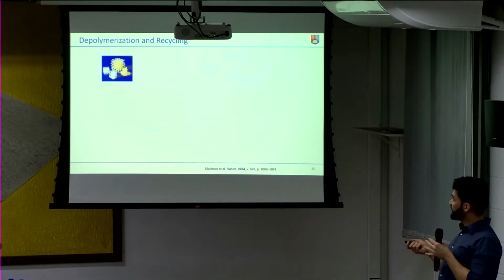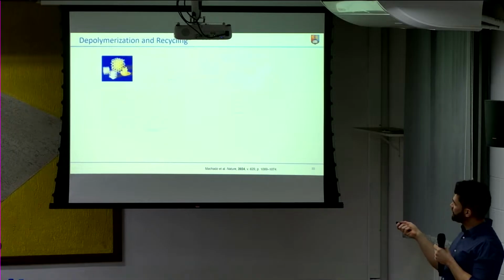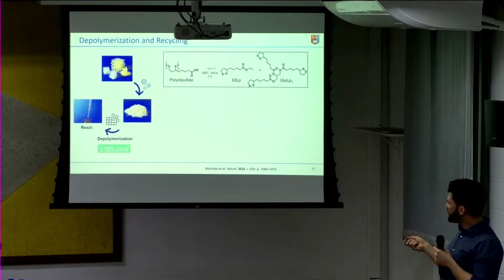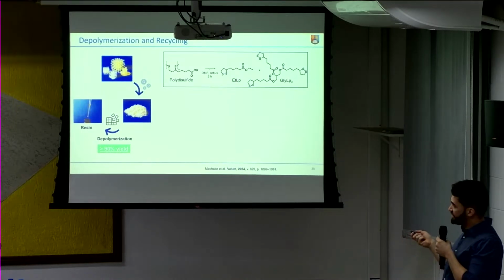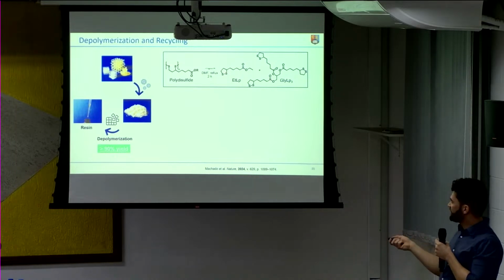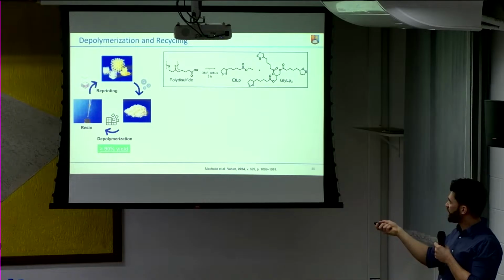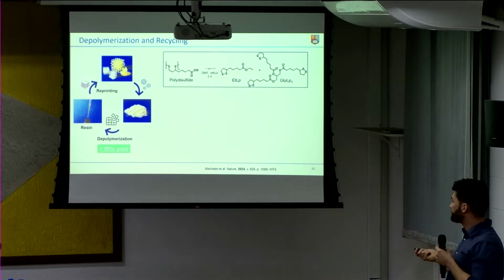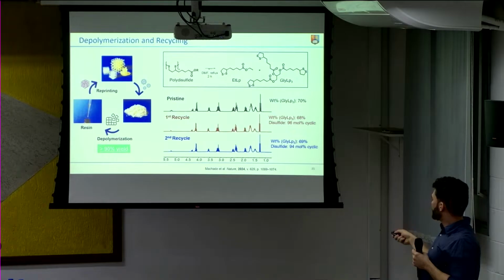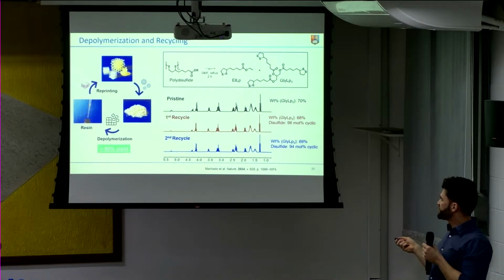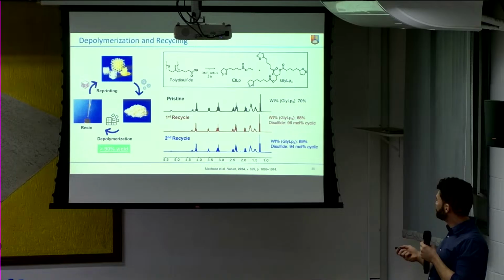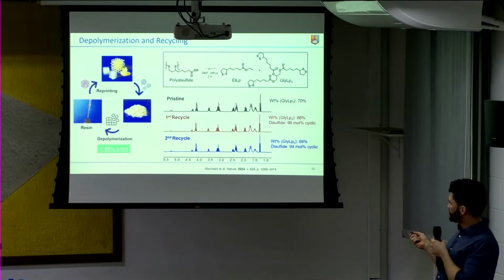So after that, we started doing the depolymerization and recycling. So basically, we got the prints, we grind them, and then we depolymerize them by just heating them up in DMF. So we have a ring closure reaction here, and the network goes back to the initial monomers with 90% yield. And then we are able to use the resin again for reprinting. And here we can see by NMR that the resins in the pristine, first recycle and second recycle are basically the same. So as far as composition goes, they're very similar.